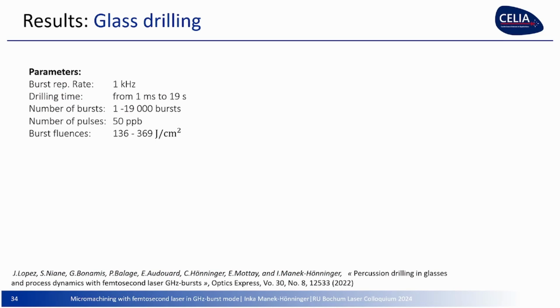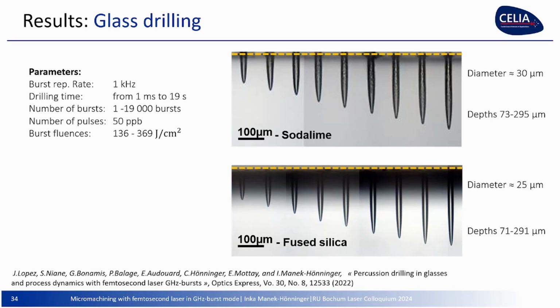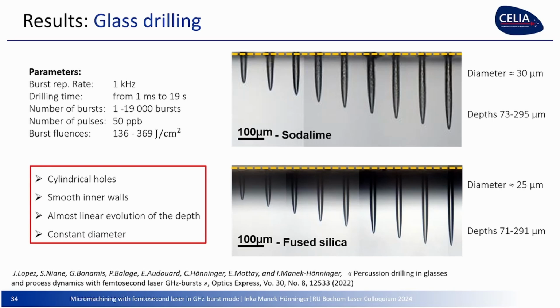Glass drilling. So here are always the parameters. Maybe I will not repeat it every time. You can just read them. And we investigated some different burst fluences. And what do the holes look like? Here for two materials, we have soda lime and fused silica. We have diameters between 25 and 30 micron. And we have depths that are increasing with the number of bursts that were applied. Here, we applied 200, 300, 400, 500, 600, and so on bursts. As we are at 1 kilohertz, that means 200 milliseconds, 300 milliseconds, etc. Here we are at 900 milliseconds, not even 1 second. And you can see there's an increase that looks linear. So we have cylindrical holes in contrast to single pulse drilling. We have smooth inner walls, very smooth in the case of fused silica. We have an almost linear evolution of the depth, and we have a constant diameter.